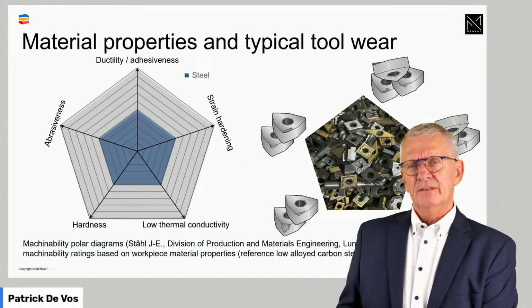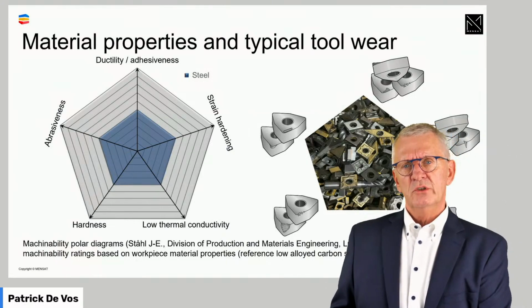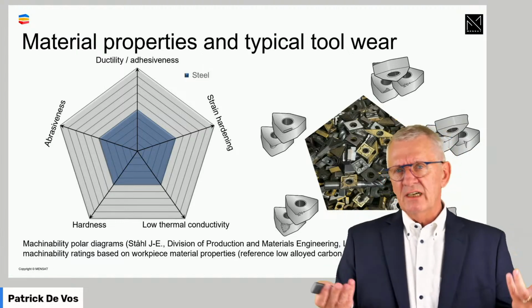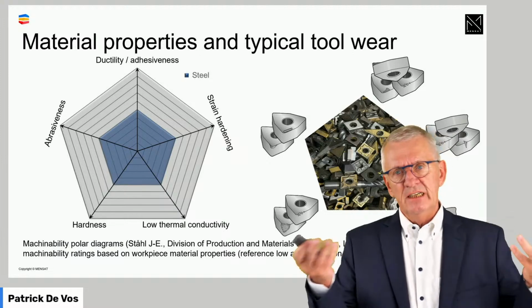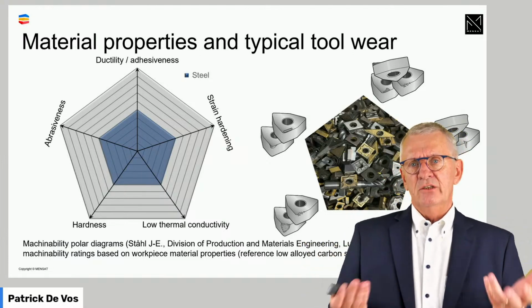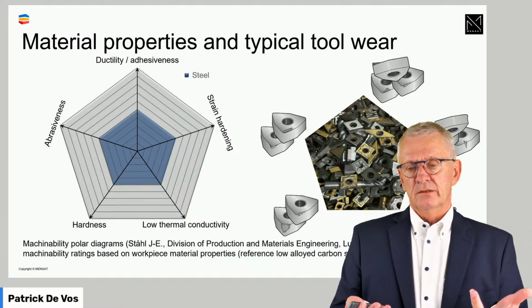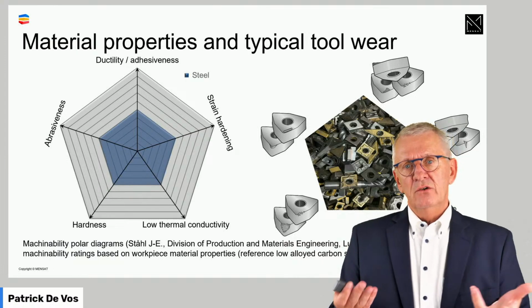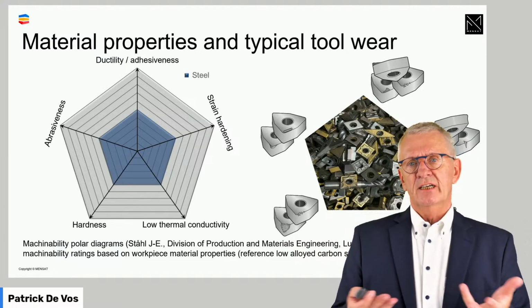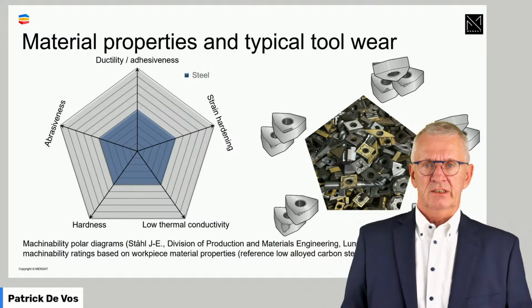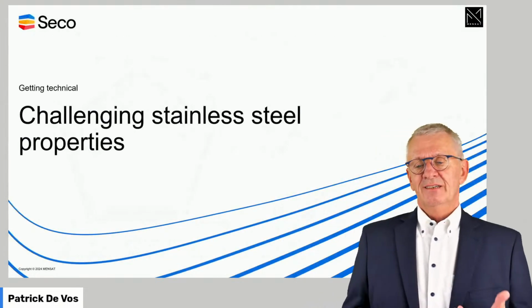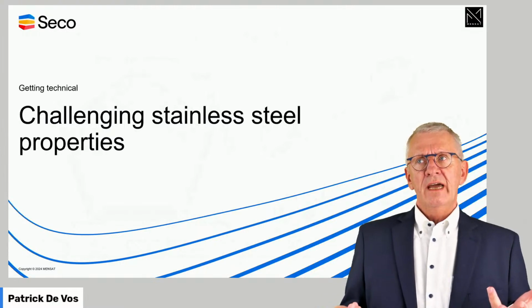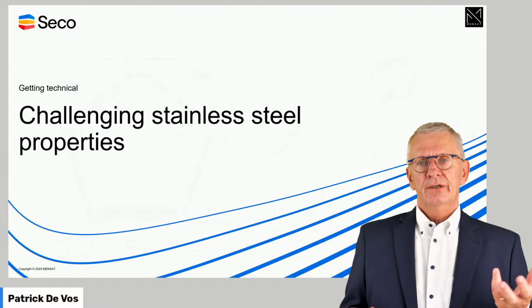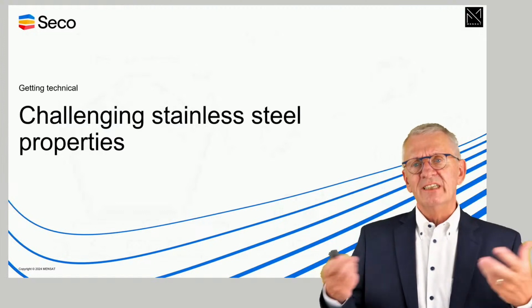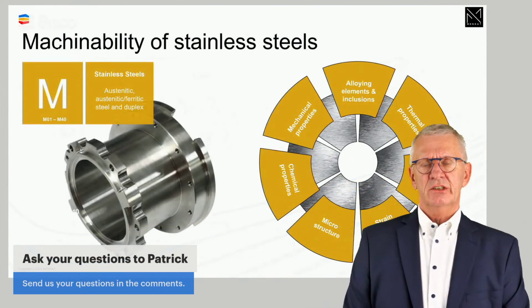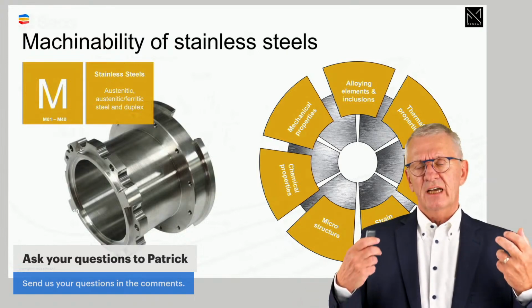And that means that if you are confronted with a material and you want to figure out how to do machining, and which tool and which carbide grade or cutting material in general, and which geometry and feeds and speeds, and you make certain selections and you observe the process and you look at used cutting edges, you can say much more precisely, okay, what I see is what I expected or not. And if not, I have to redo the exercise. I think that's perhaps the most beautiful thing about this system. It makes wear control, deterioration control, much easier or more predictable.